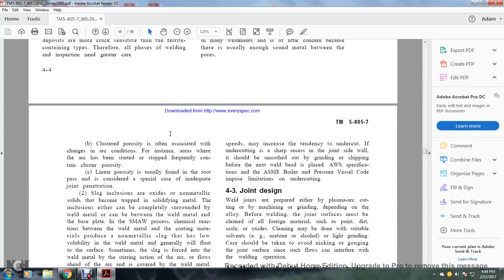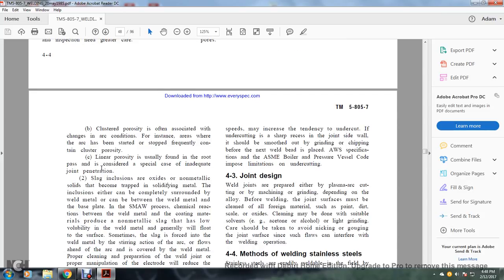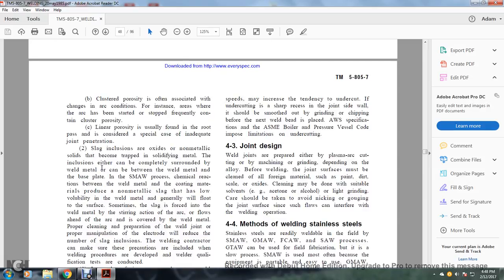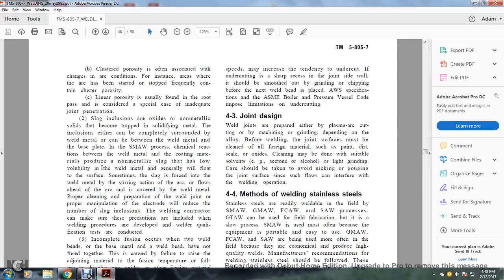Cluster porosity is often associated with improper arc starting conditions, where the arc has been started, and these starts frequently contain cluster porosity. Linear porosity is usually found in the root pass, a special case of inadequate joint penetration. 2. Slag inclusions are oxide, non-metallic solids that become trapped in the solidifying metal.